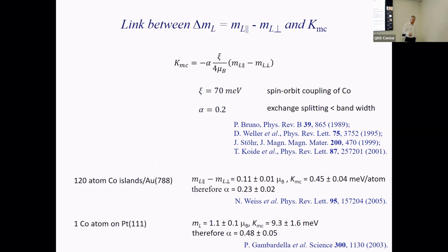There are papers in the literature that are basically postulating that there should be a very strong interaction, because in principle, if you think of a spin, the spin itself doesn't know a direction in space. It has to be isotropic. But an orbital moment is something where you can think in a classical way and say that's an electron that is in an orbit, and this orbit has a certain orientation in space. So the only thing that can have an orientation in space is an orbital moment. If you have no orbital moment, then you have no anisotropy by definition, basically. If you have a very small orbital moment, you have very small anisotropy. If you have a big one, you have big anisotropy.